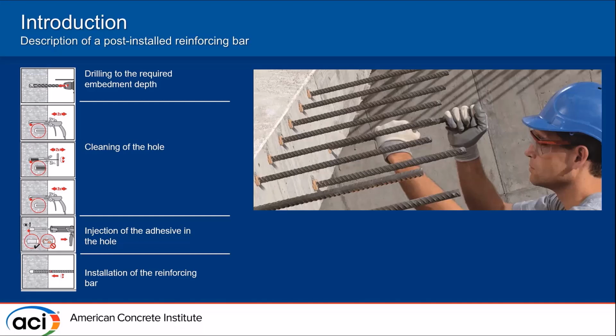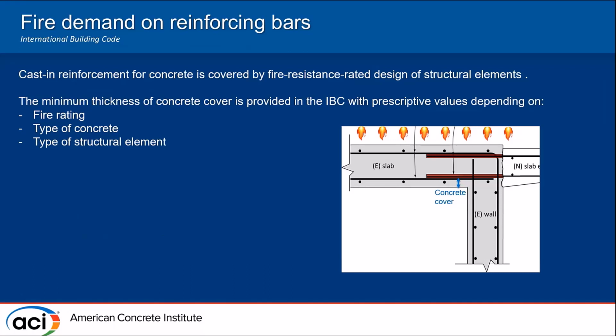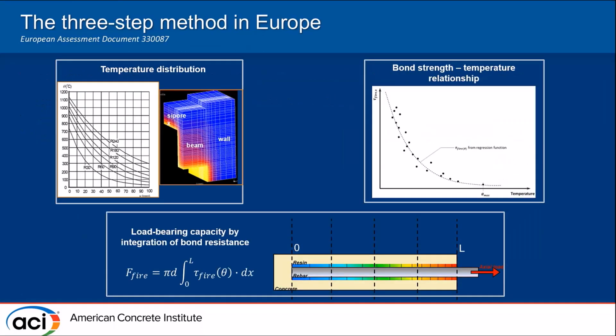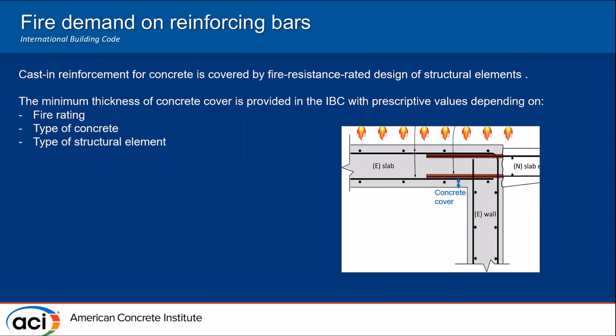And in the scope of evaluation and design, we generally separate the anchor application from the rebar application. In the case of post-install rebars, these can replace, in some cases, the traditional cast-in rebars, where there is no polymer adhesive. And the fire design of cast-in rebars is covered by the International Building Code, which gives minimum concrete covers in order to protect the rebar from the fire. So these prescriptive concrete covers depend on the fire rating we're looking for, the type of element, and also the type of concrete. In the case of post-install rebar, we have a polymer adhesive around the bar, and this makes them much more vulnerable to high temperature. And that's why there was a need to develop a design concept that was associated to this type of technology.